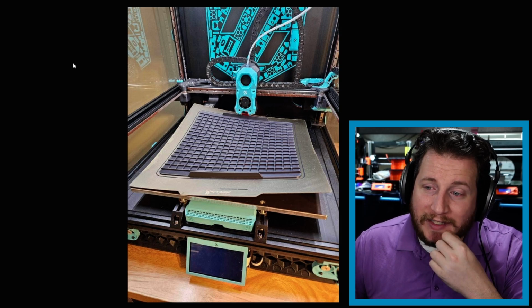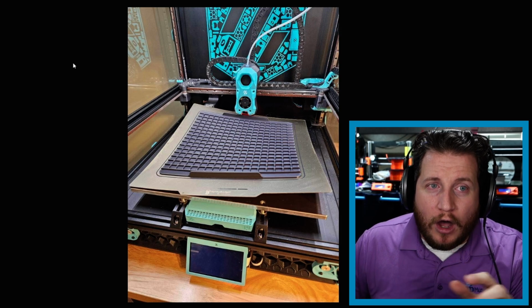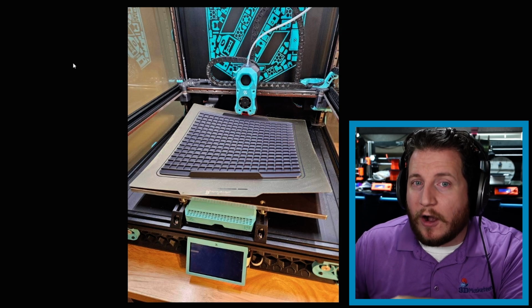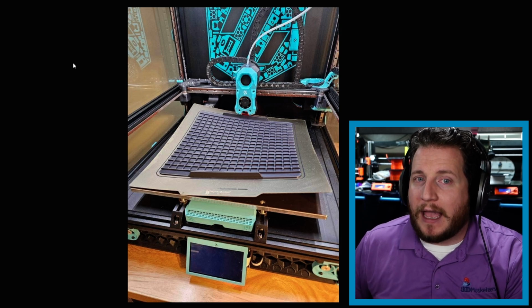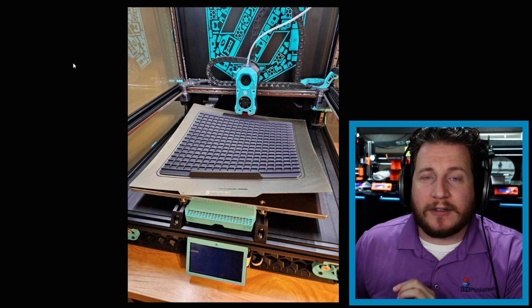In our experience, a design on the build plate similar to what we see on the top of this part with that checker pattern would reduce the amount of warping that we see, because the warping like this occurs when the whole part itself shrinks. But if its contact patch is lower to the build plate itself, right, there's less material contacting the build plate, there's less material to shrink. Therefore, you get less shrinkage on your part as a whole.